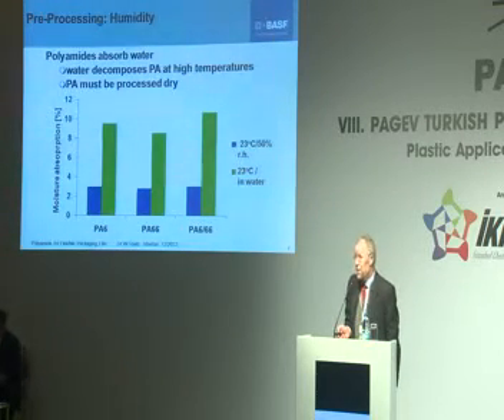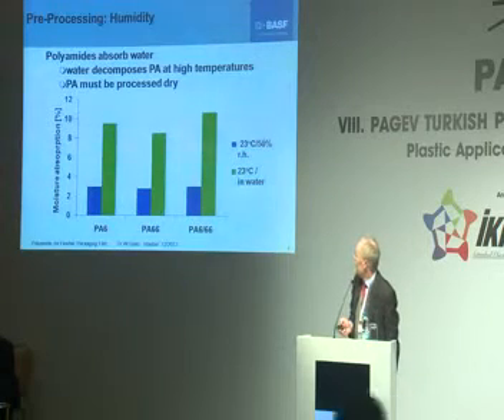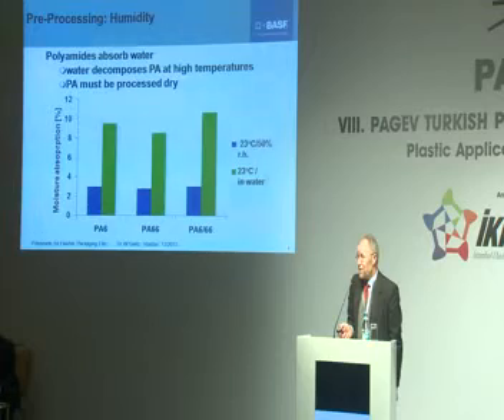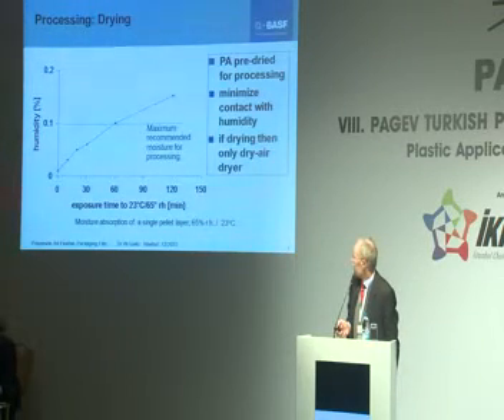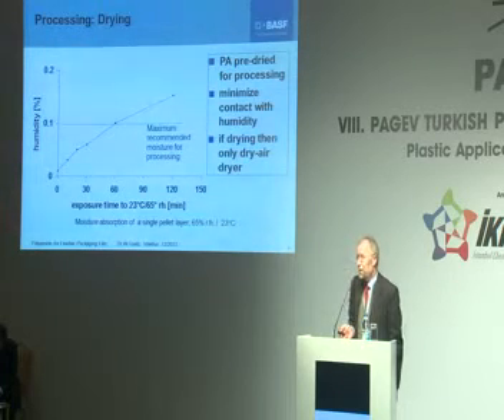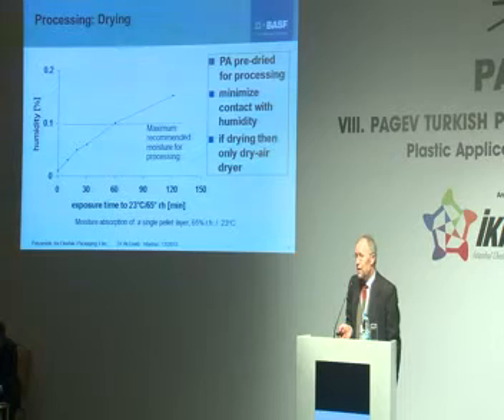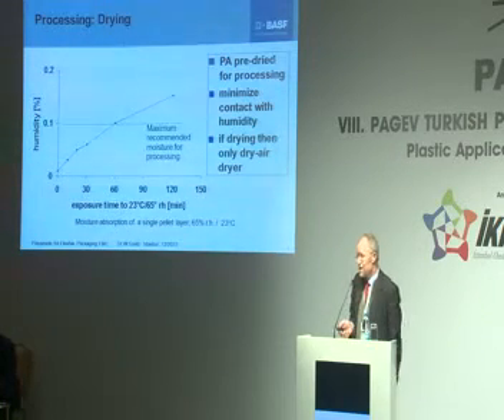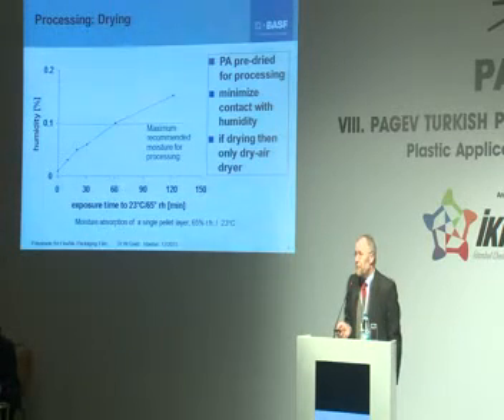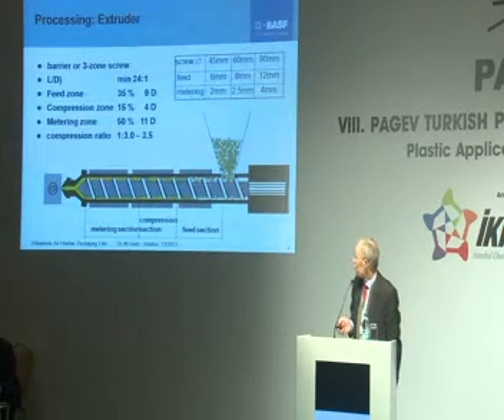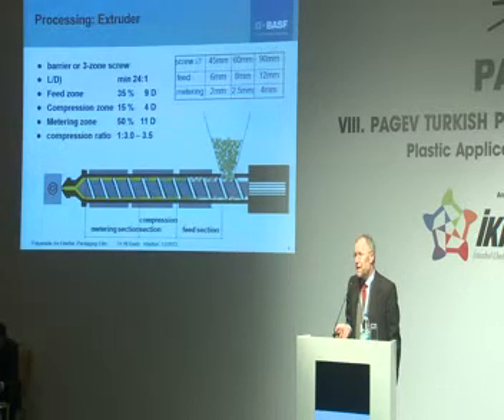Polyamides do absorb water, about 3% in standard air conditions, about 9% when immersed in water. Polyamides need to be dry at the time of processing. Even pre-dried material which is exposed for too long to humid air will within a couple of hours absorb such a moisture level that it would cause smoke, degradation, molecular degradation, and finally steam bubbles in the film that is extruded from that. Most polyamides are supplied pre-dried and need to be protected from humidity until the time of processing.